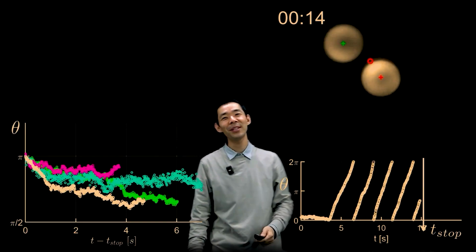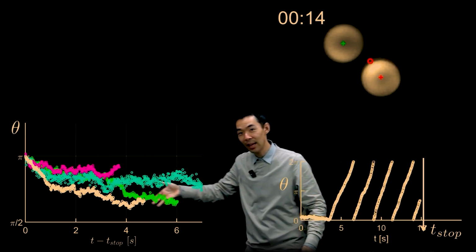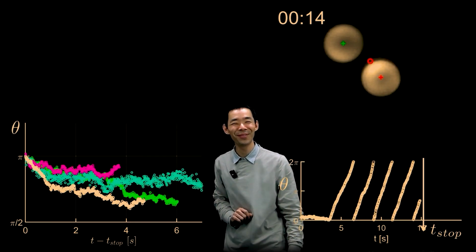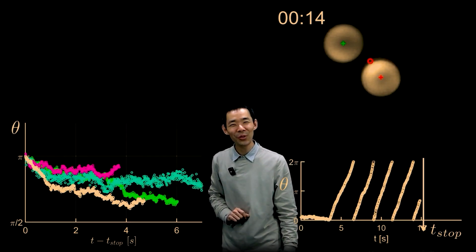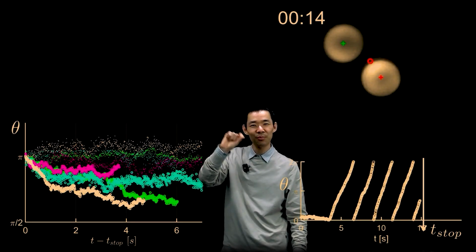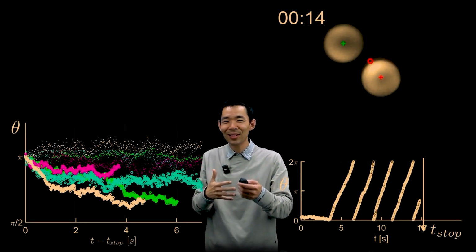And if we perform this experiment across different realizations, we all see this decay and backspin as a function of time. For the control experiment performed in water, we see that the data just has Brownian motion around exactly spot on the time that you stop the outer colloid. So clearly, viscoelasticity is creating some kind of interesting effect that's causing this reversal in the angular trajectory.